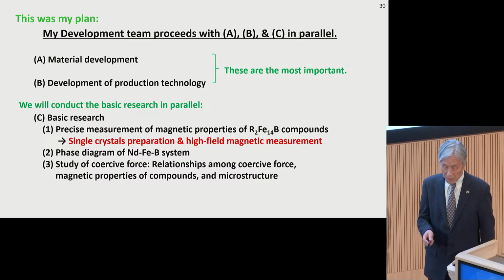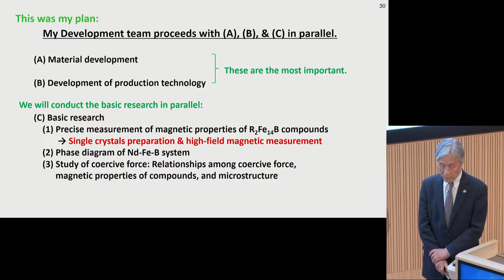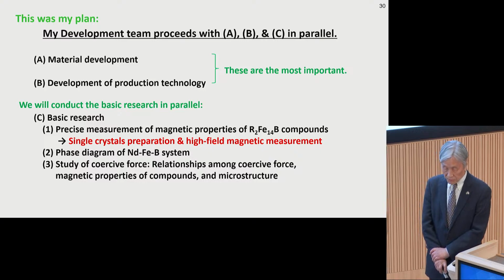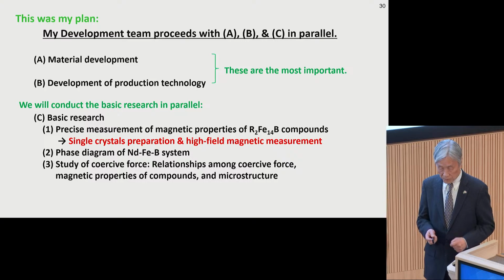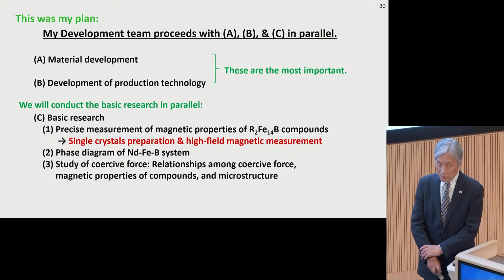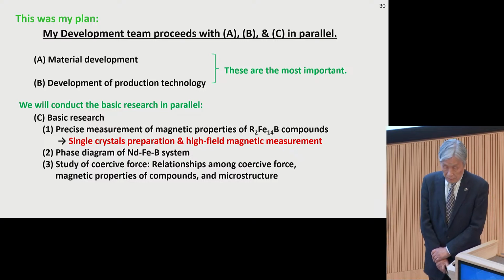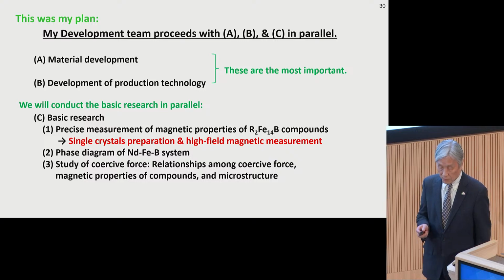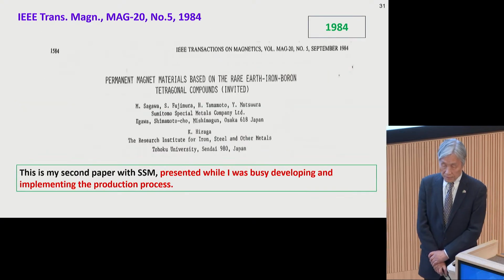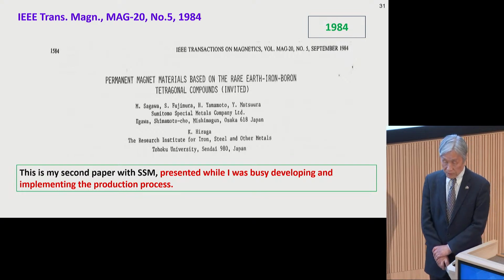Basic research. Number one, precise measurements of magnetic properties of rare earth 2 iron 14 boron compounds. Single crystal preparation and high field magnetic measurement. Number two, phase diagram of neodymium iron boron system. Number three, study of coercive force, relationship among coercive force, magnetic properties of compounds and microstructure. And this is my second paper with SSM, presented while I was very busy developing and implementing the production process.